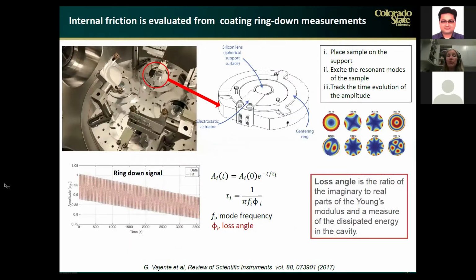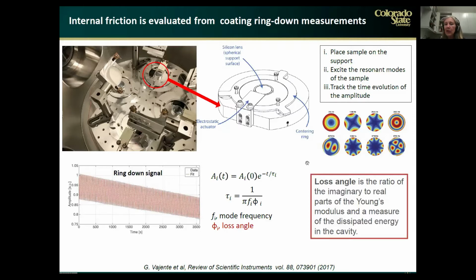So how do we measure Brownian noise? Brownian noise or internal friction is measured with a technique that is called coating ring down measurements. It's schematically shown here. The sample is placed in the center of this structure, and an electrostatic actuator makes the sample oscillate, and so we see all of these oscillation modes, and then we look at the ring down signal from these oscillation modes.